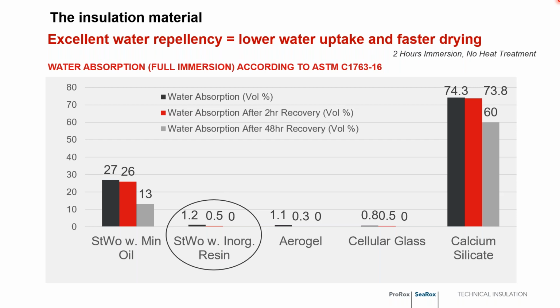And as I mentioned earlier, not all stone wools are created equal. As you can see right here, stone wool treated with mineral oil did not perform as well as stone wool with inorganic resin. The reason there's an inorganic resin, or a stone wool with a mineral, I get tongue twisted on it because there's too many minerals in that statement, is that it's just a different additive in the manufacturing process that allows stone wool to resist water intrusion. So inorganic resin results in a better situation than the stone wool with mineral oil. And you will see that in other situations as we proceed forward.